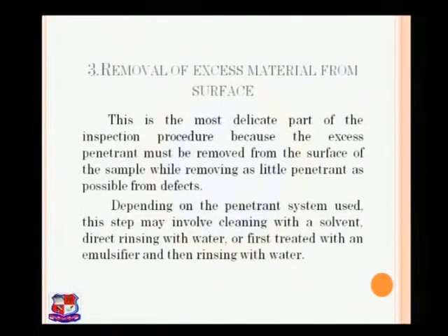If there is any kind of paint or dye there, and it is soluble in water, then water can be used to remove that. But this particular stage is very critical, and we need to take care that when we remove the excess penetrant, we do not apply too much force, so that the penetrant material which entered into the crack or flaw will not also be washed out. If it is so, then we won't be able to identify the crack.